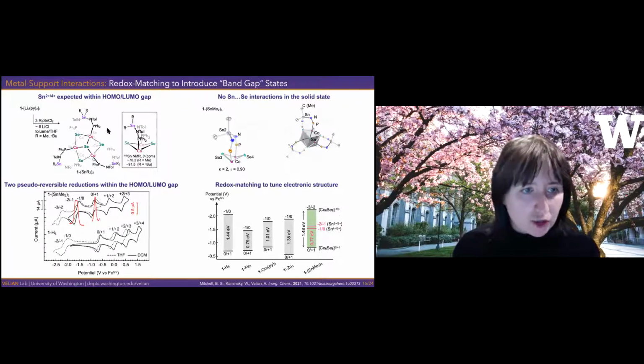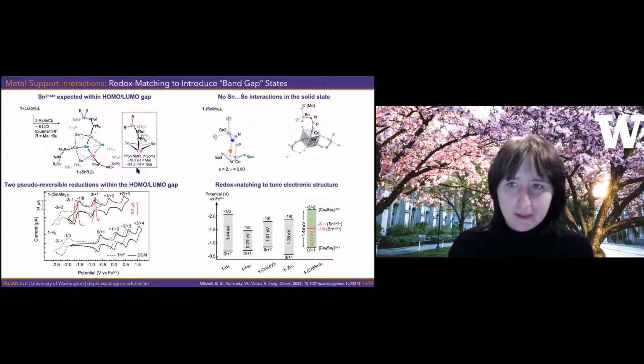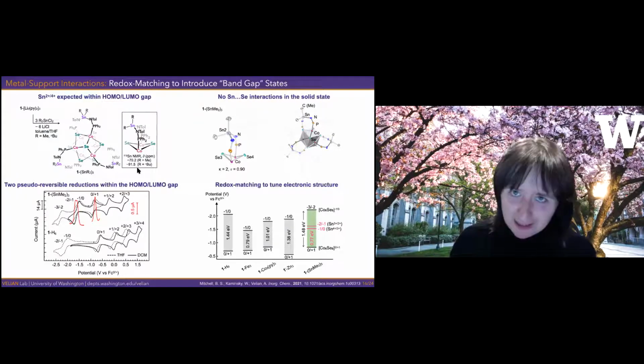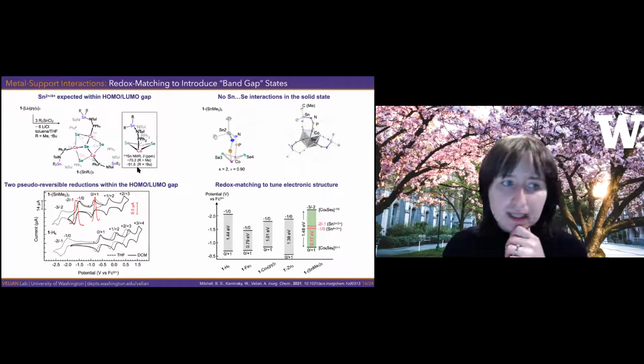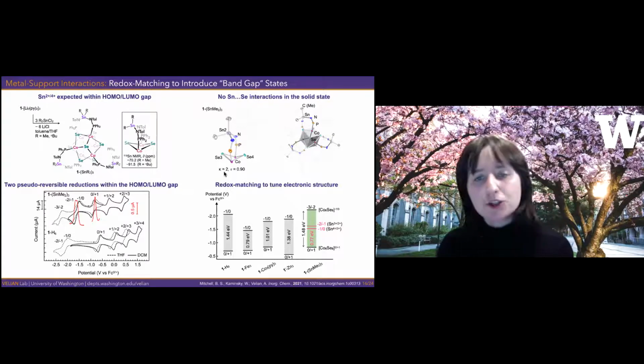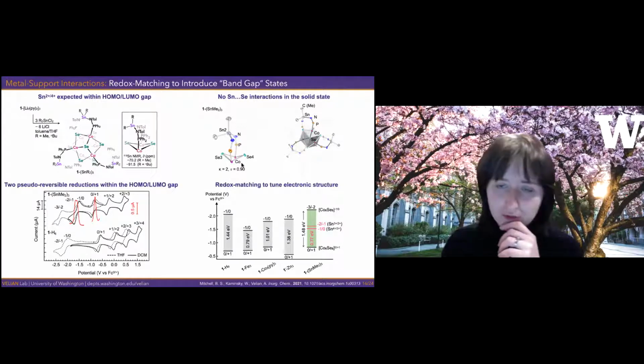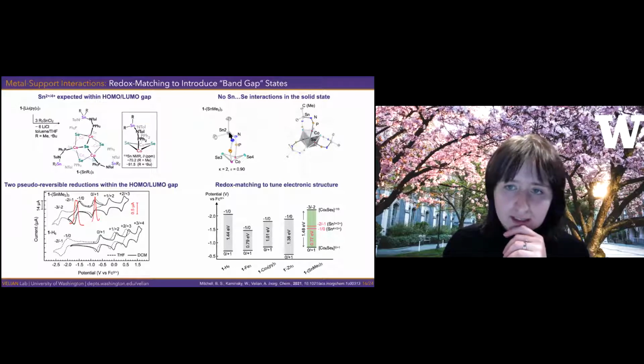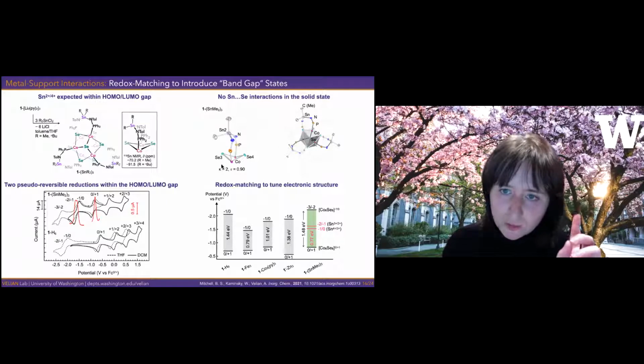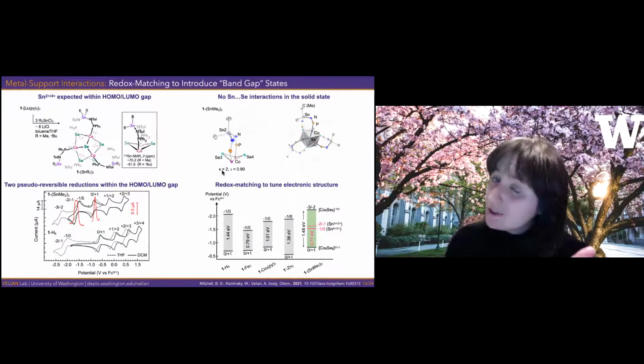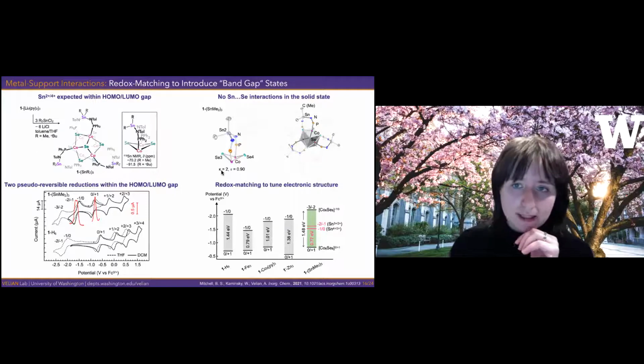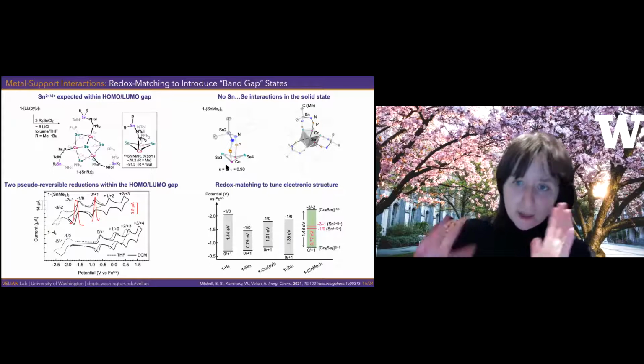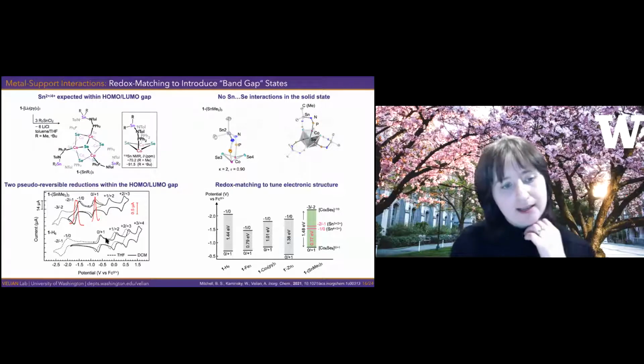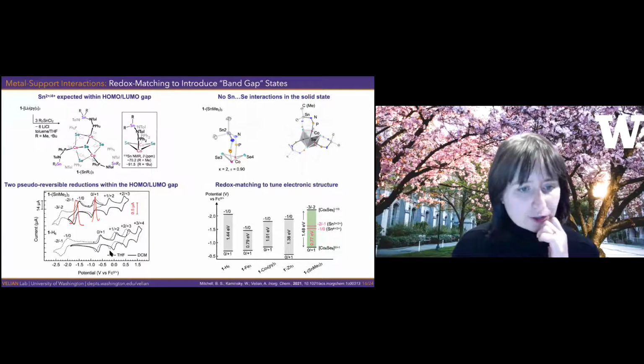So here is the synthesis of the tritin cluster. The tin is now a dialkyl tin, which is again anchored by the two amides in the way I'm showing you here. Beautiful NMR spectroscopy because you have tin, phosphorus, selenium, proton, carbon. So really nice NMR. I'm showing here a snapshot of the edge site only. This is again single crystal X-ray diffraction. One thing to note here is that the tin of all the compounds we made is the only one that does not have binding interactions with the selenium, even if tin 4 coordinated to 5 or 6 atoms is actually quite common. But let's test our hypothesis, and what we see here on the left is the electrochemistry of this cluster.